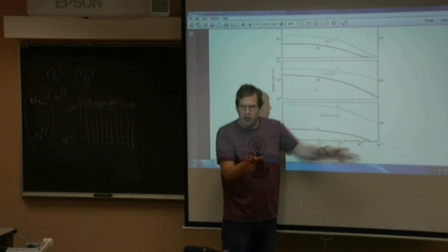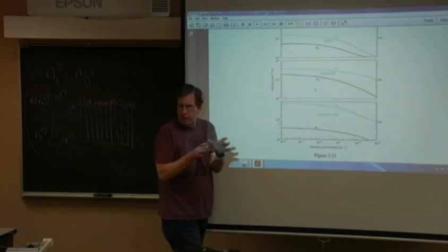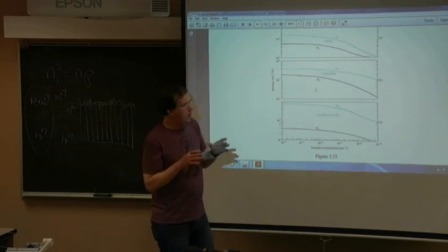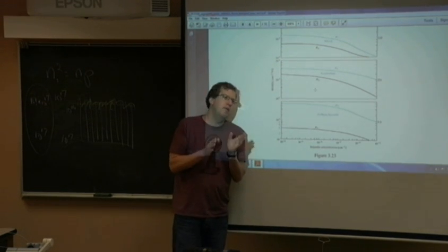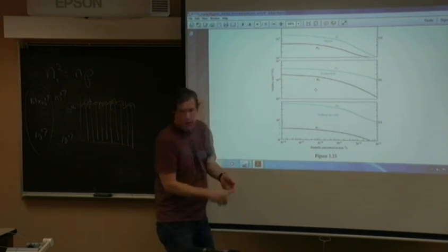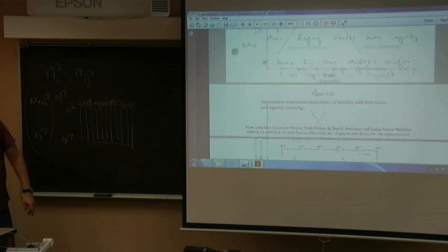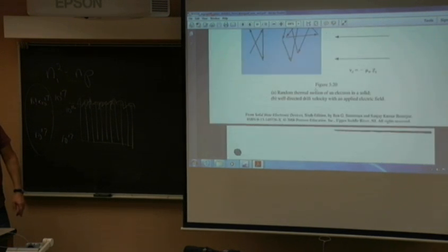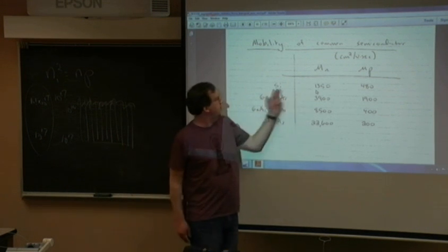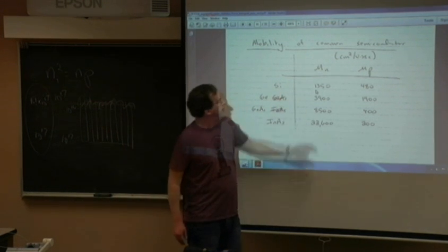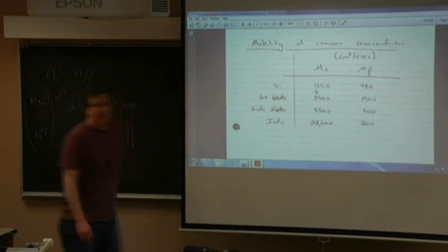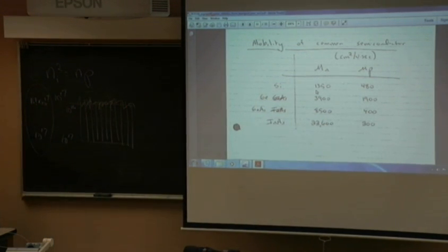So the textbooks we have, the reference ones or the one on record, all probably have a table that shows you nominally what the mobility of a semiconductor is, what silicon is, the gallium arsenide and all that. In fact, this is that table. The tables will say silicon is 1350, and the holes are 480. You don't see that when you actually build a real device,